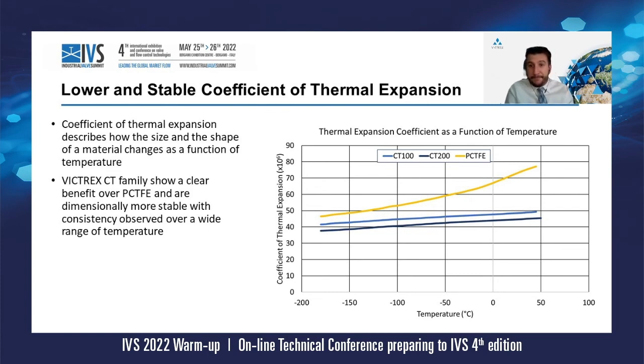The graph shows data only up to 50 degrees—the gap at higher temperatures can only increase. We can stop the comparison around 100 or maybe 120 degrees, where PCTFE is not even usable anymore, while PEEK CT100 and CT200 will continue to work properly up to 150, 180, 200 degrees, depending on pressure.